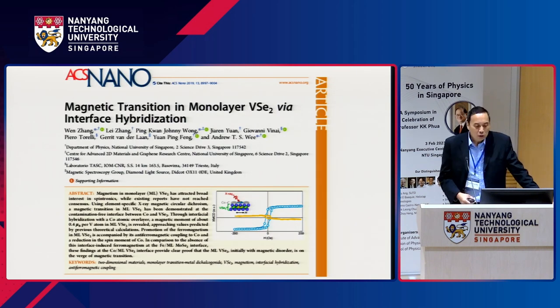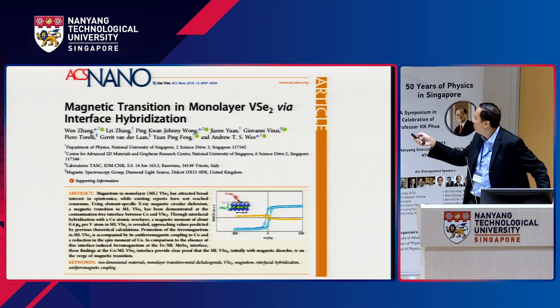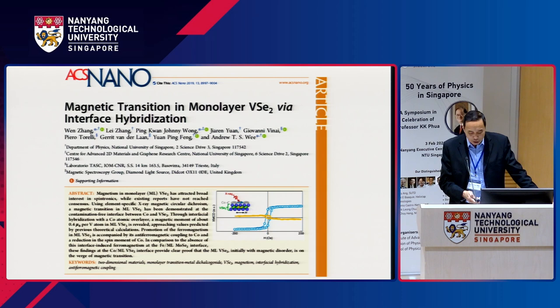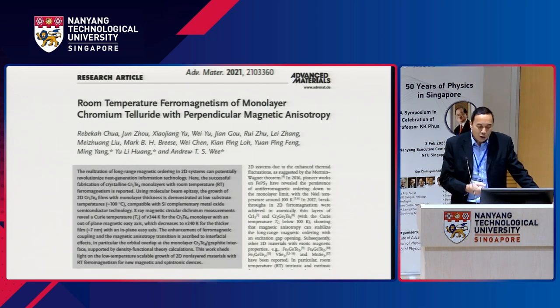Okay, so although there was spin frustration in these materials, they were not magnetic, they could easily be made magnetic. And Zhang Wen, another RF, showed that by depositing some cobalt, which is a ferromagnetic material, on the surface, this is the XMCD hysteresis, you could see the cobalt hysteresis loop and the vanadium hysteresis loop here. You could make the surface magnetic. So you have introduced some asymmetry in the system through this surface layer of cobalt. And we also showed that defects could make that same material magnetic through introducing asymmetry on the surface.